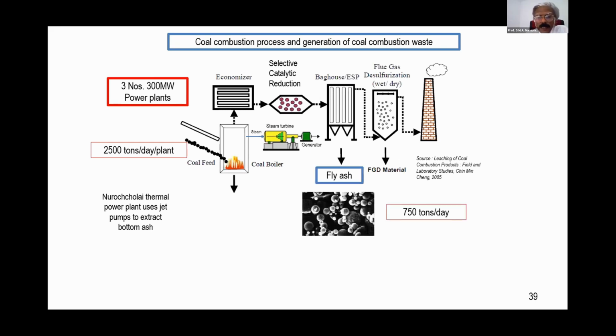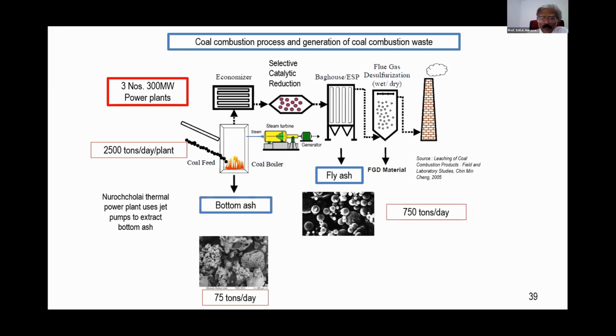And what are the waste materials coming out from this? There are 2 waste materials. One is the fly ash collected at the baghouse, the electrostatic precipitator. So very fine particles, spherical in shape. The quantity is about 750 tons per day. And the other waste product is